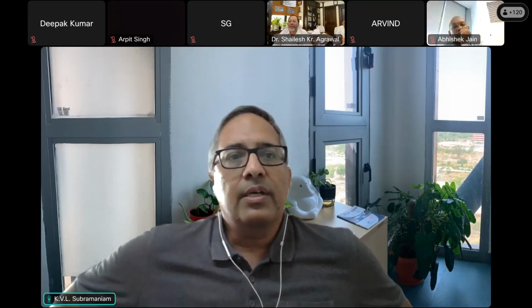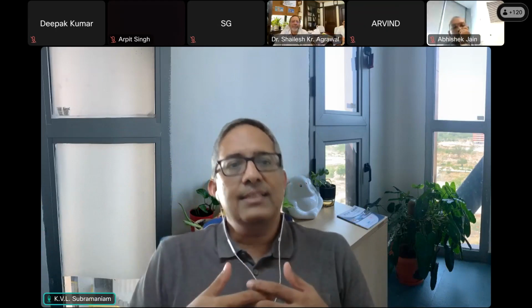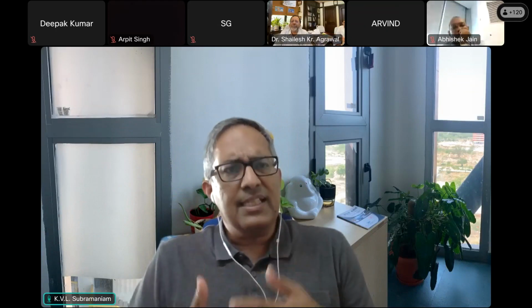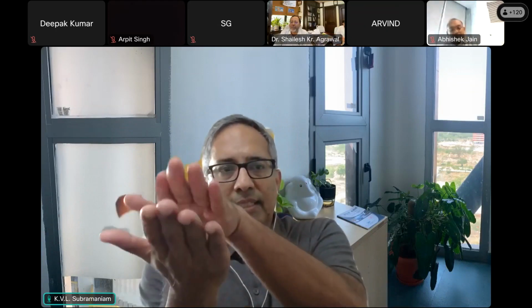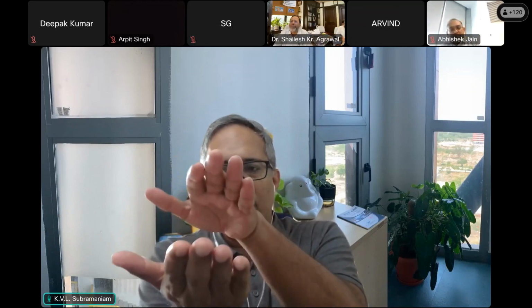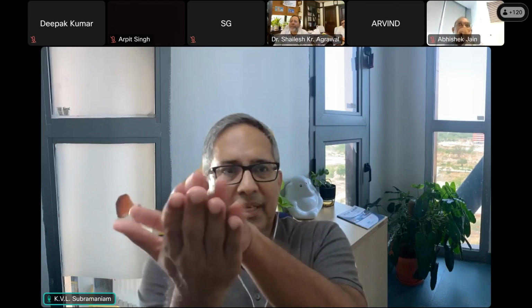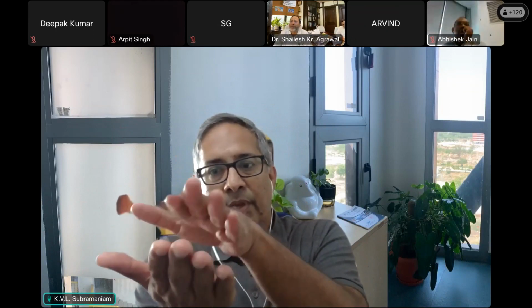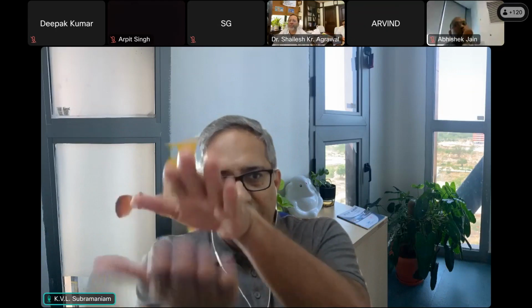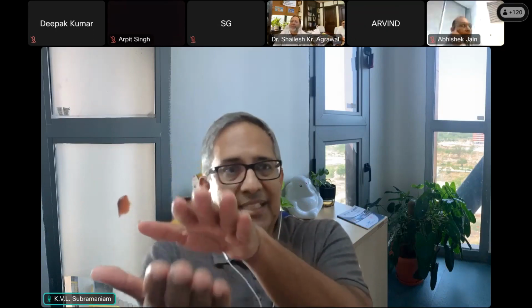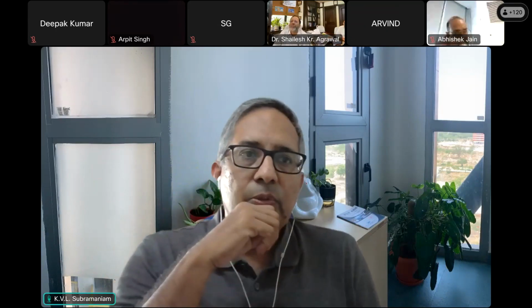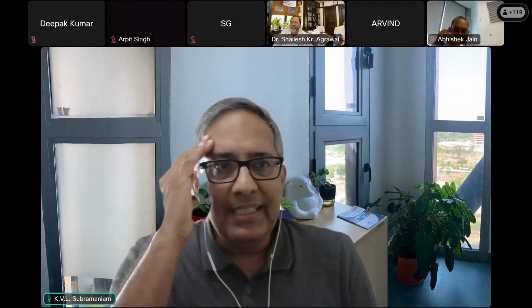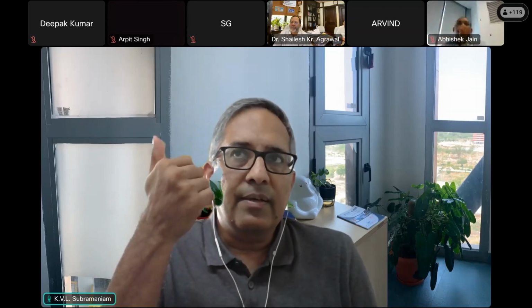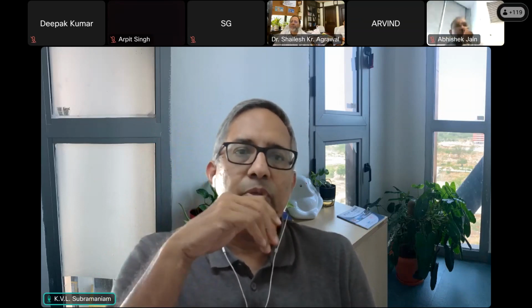What we are working on right now is called functionalizing the interface. The interface is the Achilles heel. When two layers come together, layer to layer, they're just bonded together by the cement paste at the interface. So when you try to pull it across the layers, it's the weakest direction. We're trying to strengthen that by functionalizing that interface, using different sprays and coatings to improve it.